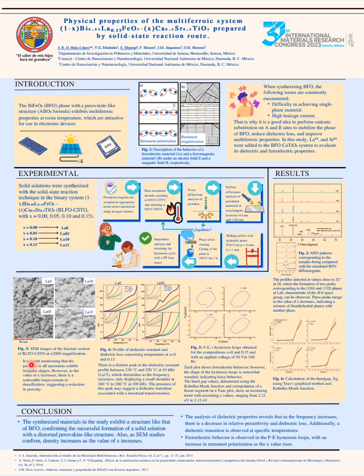Figure 3 shows the SEM images of the fracture sections of the pellets, with all specimens exhibiting irregular shapes. However, improvement in densification can be observed as the value of X increases. Figure 4 shows the relative permittivity and dielectric loss profiles with respect to temperature for samples lanthanum 0 and lanthanum 15. As the value of X increased, a peak formed between temperatures of 230 degrees Celsius and 250 degrees Celsius, which decreased in size at higher frequencies. This behavior is typical of dielectric relaxation.